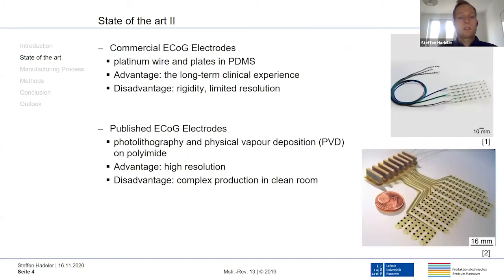The commercially available electrodes for electrocorticography are made of platinum wires and plates in a PDMS, and the electrode spacing is about 10 millimeters. The advantage of these structures is the long-term clinical experience with PDMS. But the disadvantage is the stiffness and the limited resolution of these electrodes.